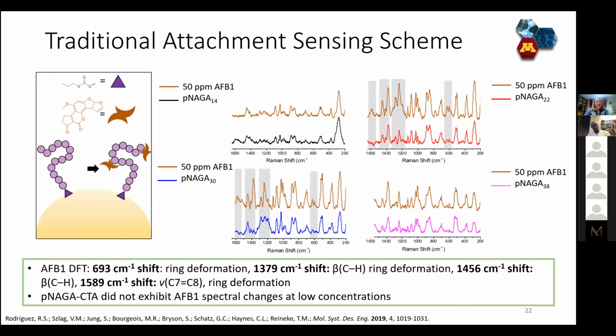I will orient you. So this is our NAGA polymer with the trithiocarbonate end group, and we stuck it on the surface in advance, and then we flowed the aflatoxin over. And what you're looking at is the 4 different chain lengths of the NAGA. So in black is the 14 mer, in red is the 22 mer, in blue is the 30 mer, and pink is the 38 mer. And what you're seeing in those colored spectra is the polymer only. And then in brown, in all cases, is after we've exposed it to 50 parts per million of our target.